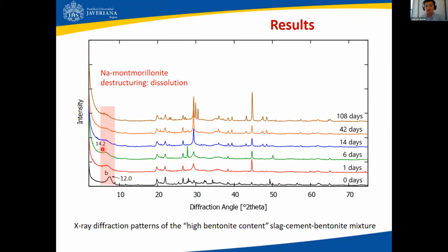These findings were also confirmed in the high bentonite content sample. So you can see here again the peak, and again, the fading of the peak as the time moves forward towards 3 months, basically.